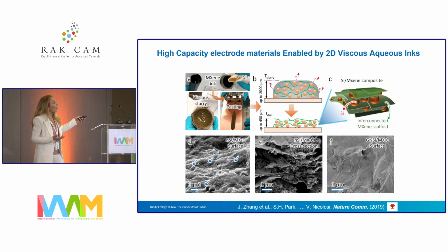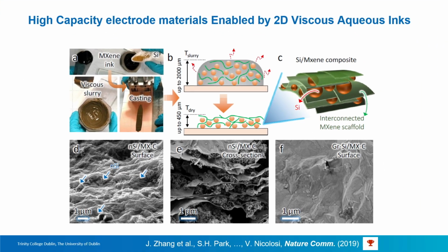Our approach instead was to hit two birds with one stone, using a 2D nanomaterial, MXenes in this case, that is electrically very conductive and also mechanically very robust. So that's exactly what we did. We used exfoliated MXene inks like the ones I showed before, and by simple slurry casting we made a viscous slurry cast on a current collector. What we realized was that the electrode self-assembled into what we call a sort of segregated network.